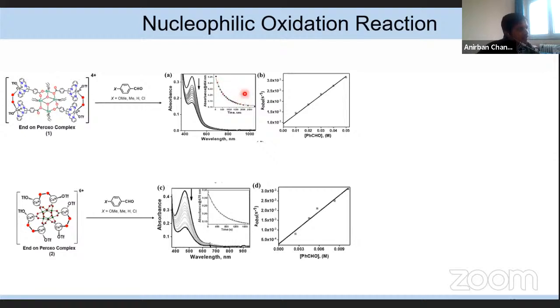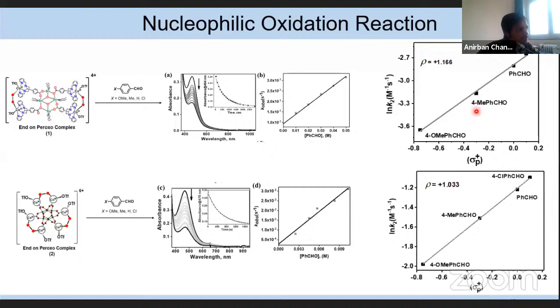And from this k observed value, I determined the second order rate constant k2 for benzaldehyde. The same experiment was performed using different para substituted benzaldehydes, and from the different k2 values, I determined the Hammett plot. And you can see the Hammett plot is positive, which confirms its nucleophilic behavior.